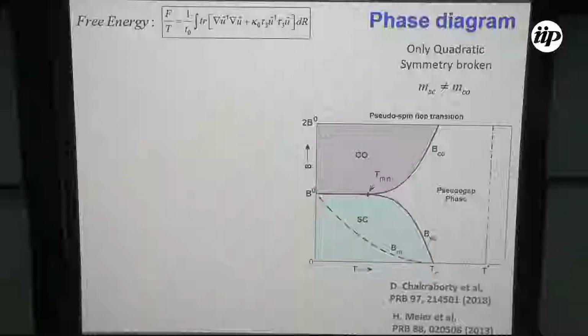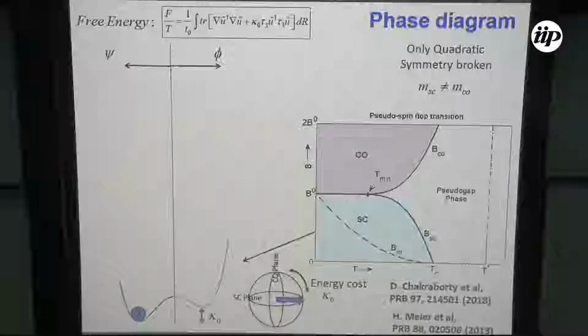If you look at the phase diagram, it looks like this, where we will see that there is a superconducting to charge order transition. And in order to understand it, let me go to one line, the t equal to 0 line. So let's see what happens. If we are at low field, if we look at the free energy in the superconducting direction and the charge order direction, there is a minimum in the superconducting direction which is at a lower energy than the minimum in the charge order direction. As a result, the system is in the superconducting phase and the pseudo-spin is in this plane.